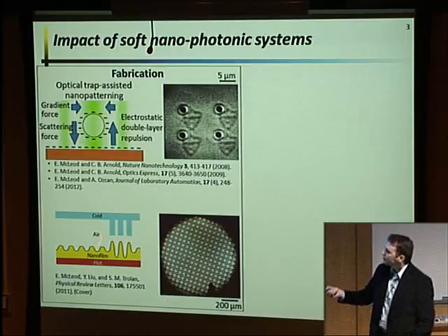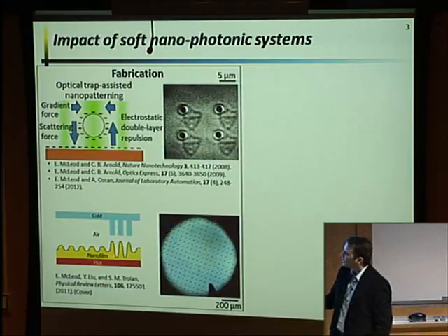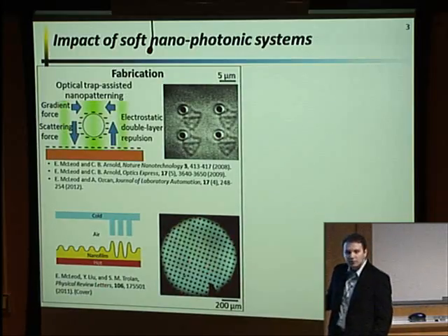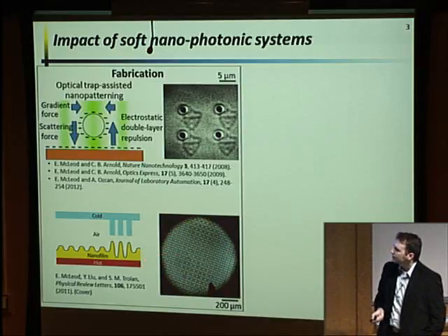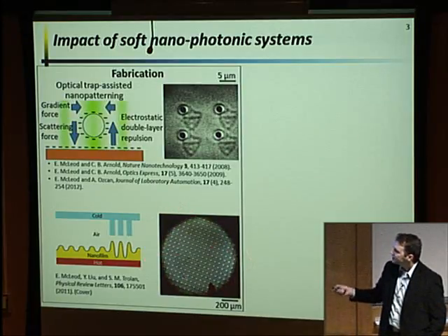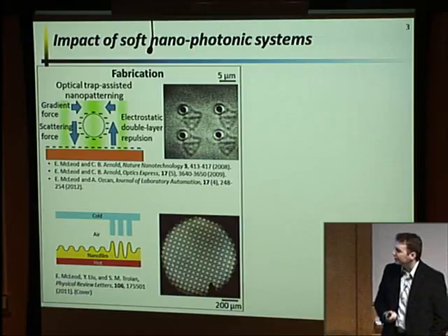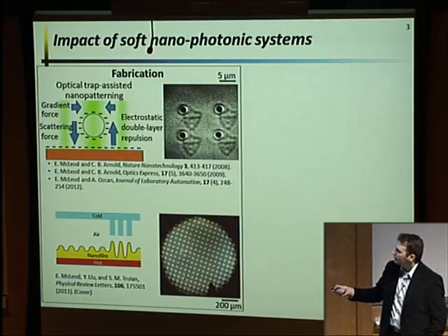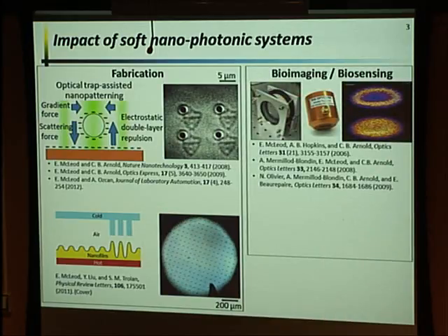There's a strong temperature gradient that we impose across this, so a cold plate on the top and a hot plate on the bottom. This leads to a destabilization, or an instability, in the polymer film. So rather than remaining flat, it spontaneously forms these ripples. And we can seed where these ripples are going to be formed if we structure this top plate. So this would be an example where we're creating something like a microlens array. This is an array of small bumps on a surface that could be used, for example, to focus light.